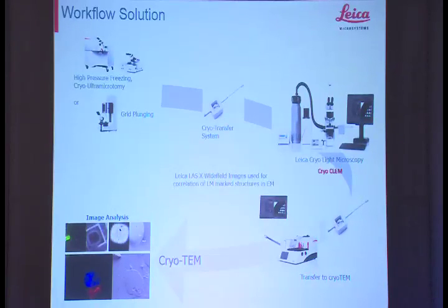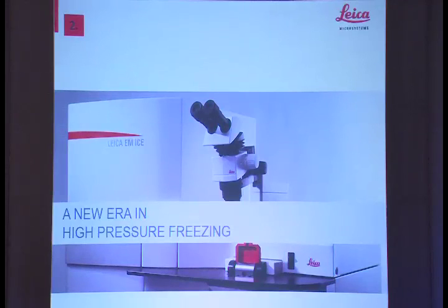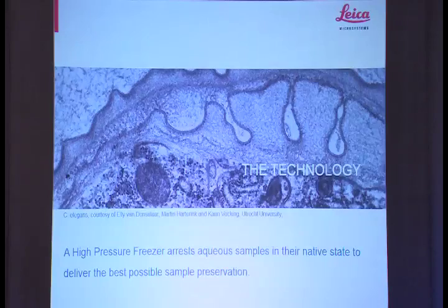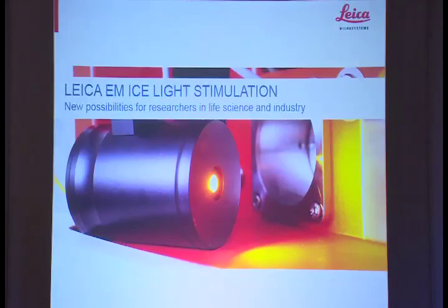So this is one of the important workflows which we've been working on, and it often starts off with high pressure freezing. High pressure freezing is a very, very useful technique. If you're not working on single particles and plunge freezing, this is the preferred technique for preparing samples. What we do is we take a sample and we put it under 2,000 atmospheres pressure and then freeze. And by doing this, we can produce a vitreous sample. And this technology is now used not only on its own, but we've started to utilize high-pressure freezing to involve other techniques as well. And the other techniques involve light stimulation.